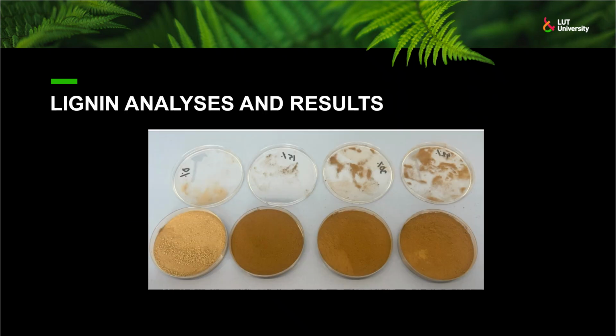Lignin analysis and results. Before the analysis, samples were dried at 40 degrees Celsius and crushed with a mortar and pestle to reduce particle size. The particle size was neither standardized nor measured, but this is assumed not to affect the properties of lignin samples in the following analyses: dry matter content, elemental analysis, ash content, molecular mass, and thermal properties, namely glass transition temperature and swelling, were measured. The sulfur-free soda lignin had a beige color. It was markedly lighter than lignin containing sulfur. No differences were observed in the drying or crushing behavior between the samples.